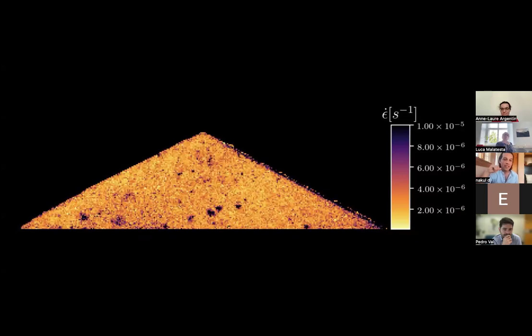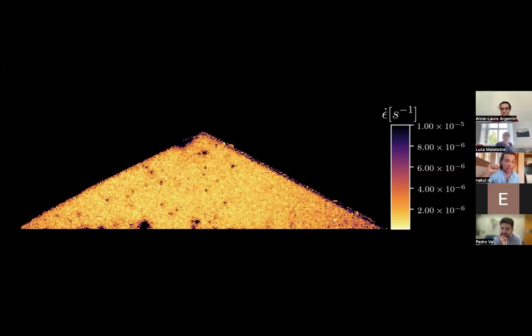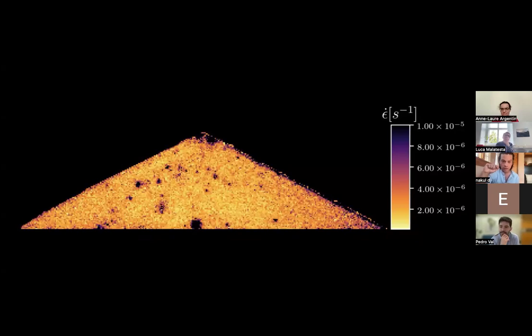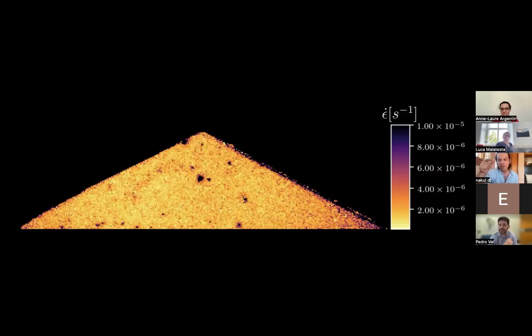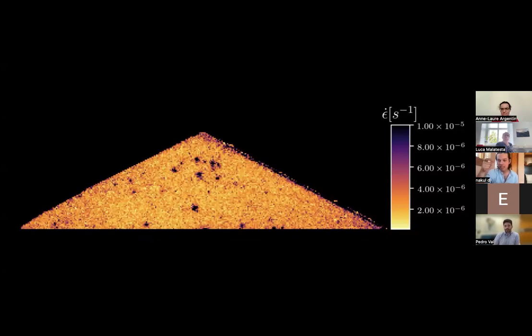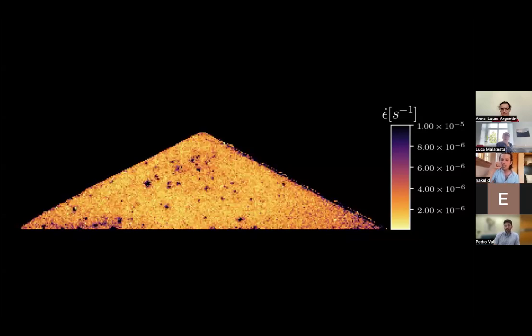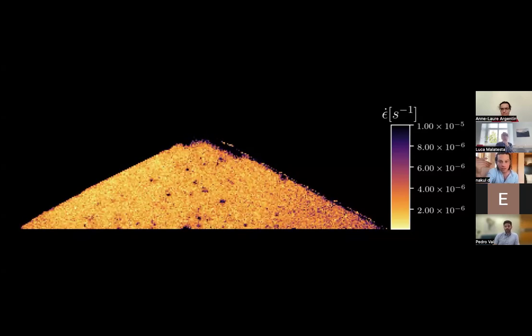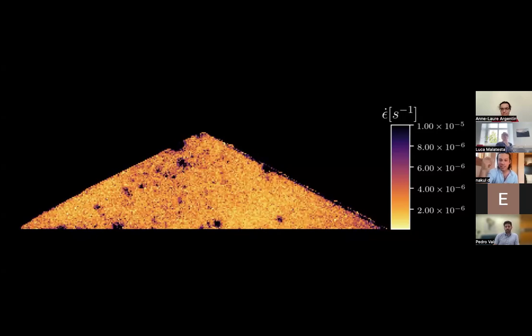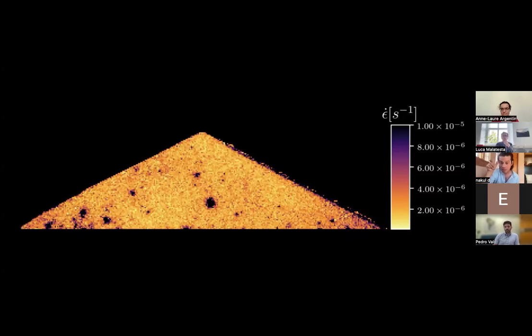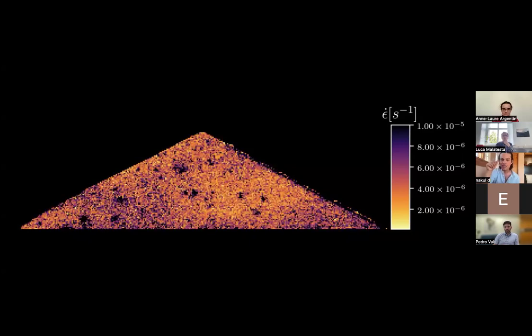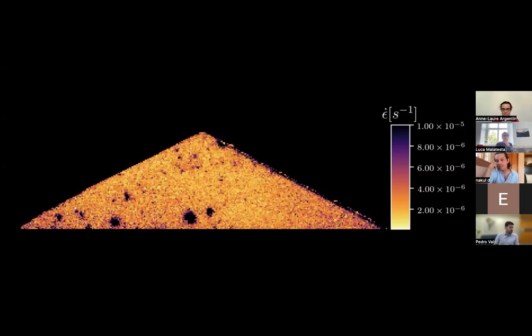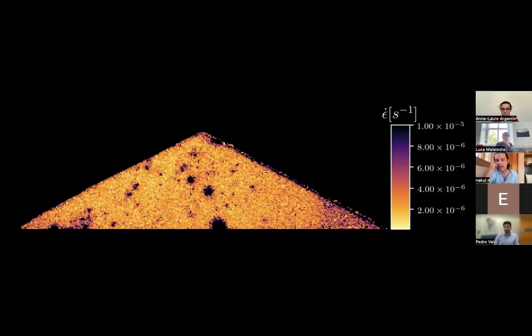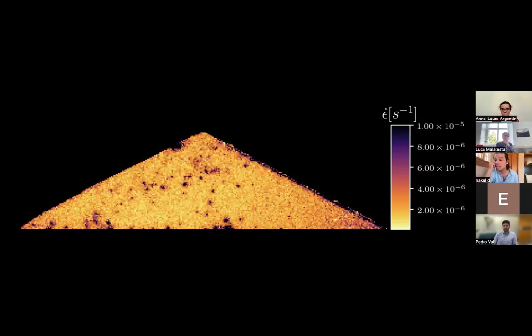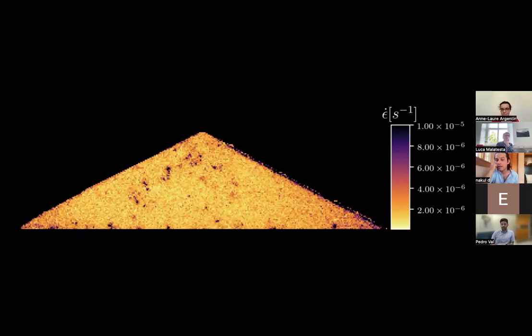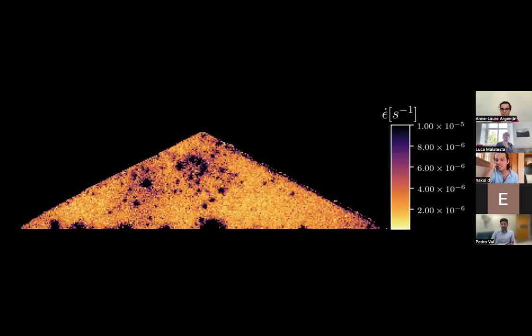The other technical point is that in order to do the spatially resolved version of diffusing wave spectroscopy, you need to know something about the scattering characteristics of the grain, and that limits the boxes that you're looking at. So for the other materials, we don't actually have such a good idea of relating the grain size to the boxes that we should use. And that prevents us from making an explicit count of the size characteristics of these rearrangements. But it should be done, and it will be done in a different experiment.